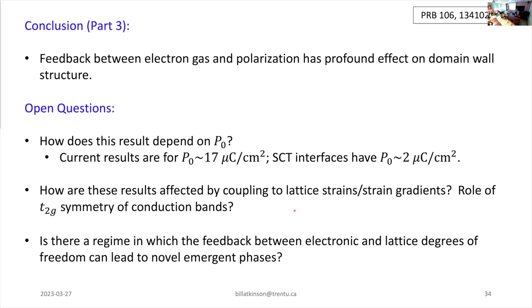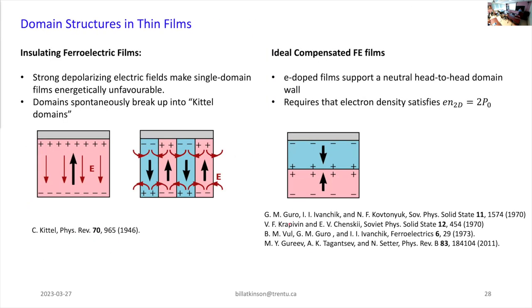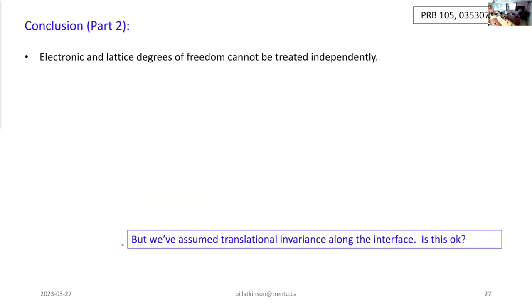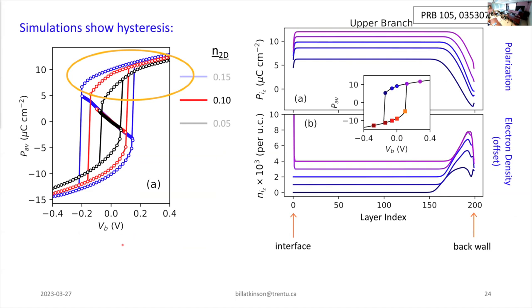So you're talking about actual local filling. It depends where you are, of course. If we look at this slide, you can see that I'm multiplying my electron densities by a factor of 1,000. So 2 × 10⁻³ is a typical electron density per 3D unit cell. These are really very low densities, so we're far from any strong correlation. You never need to worry about two electrons. That's right.